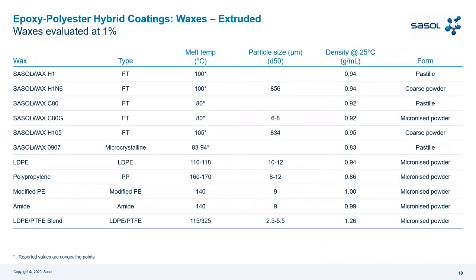So here is an overview of the waxes that we use in extrusion. 1%, as I mentioned before: Sasol wax H1, H1N6, C80, C80G, H105, and the microcrystalline 0907. You can see they are all Fischer-Tropsch except Sasol wax 0907. The melting temperature, before I told you the congealing point, now the melting temperature is 100 for the first two, 80 for the C80, 105 for the H105, and 93-94 for the microcrystalline. Then, of course, you can see the form. Some are pastillated, some are coarse powder, and some are micronized powder.